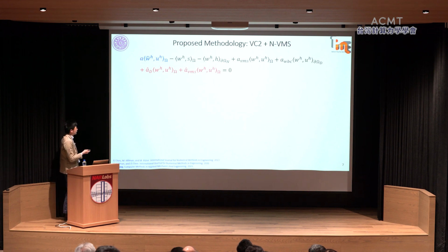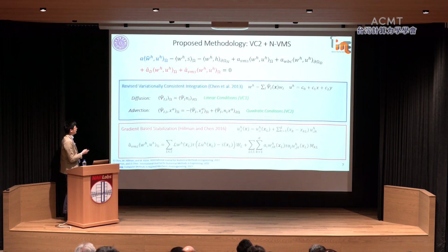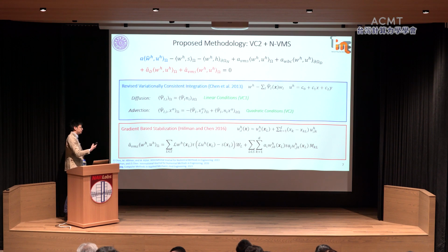So in order to address that, I basically borrow this idea from JS' earlier work. One is called variational consistent integration. The other is called NSNI, which is a gradient-based stabilization. So for the first one, the accuracy loss is due to the inability of the approximation, especially for the test function, to reproduce Galerkin exactness in the variational equation, especially for the advection term.